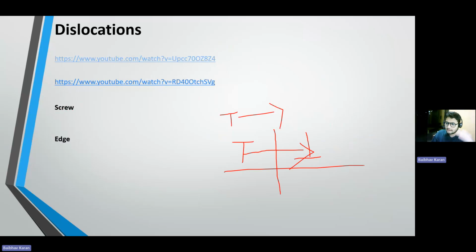That means, according to theoretical strength, what do you remember? The strength will be increasing. The material strength will be increasing because they're dislocation free. So now if the material is reduced to the nanometer range, they are more becoming dislocation free. That means they are more tending towards the theoretical strength observed. This is what you have learned in this week.